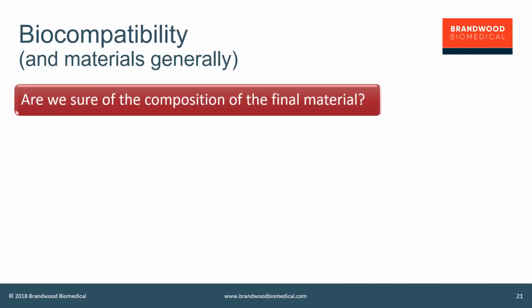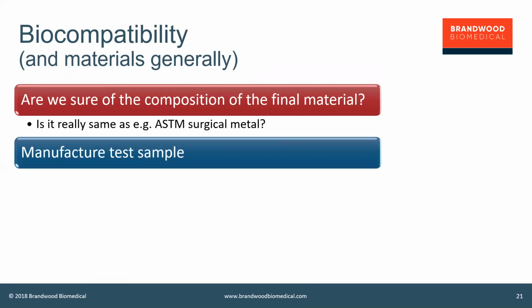So looking at that, the question is, are we sure of the composition of that final material? Is it really the same as, for example, a mass-produced ASTM surgical metal, which might be forged? And so how do we do that? Well, manufacture some test samples, use your additive manufacturing to make test samples. The beauty here, of course, is the ISO standards call for particular sample configurations because most of this work is done by